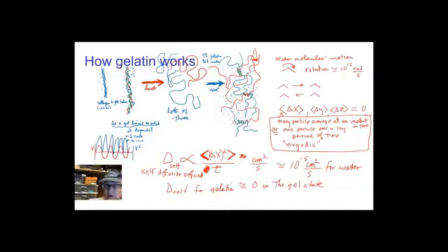The water can hardly tell anything has happened. The gelatin did have a diffusion coefficient in this state. When it was in the melted state, it had a diffusion coefficient of maybe 10 to the minus 8th square centimeters per second, and it goes almost to 0 once the gel forms, at least for most of it. There are, by the way, little bits of gelatin that hang around and don't ever join in, so those ones are still moving.